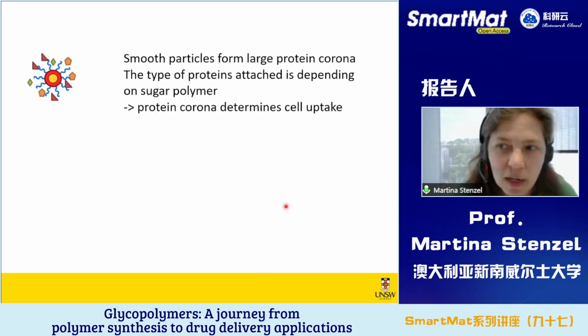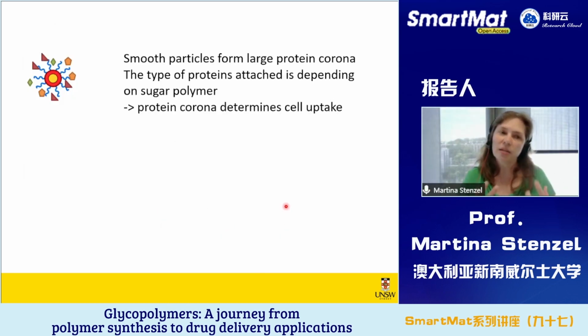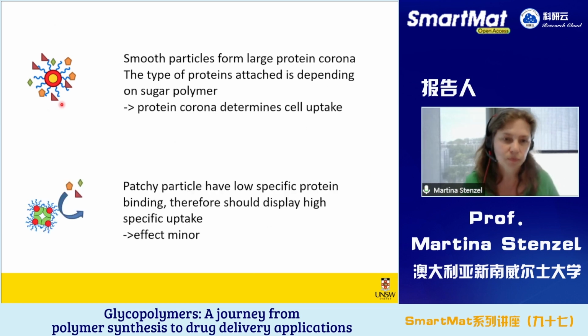So this was a very interesting lesson to learn, that there is a reason why nature's particles have this shape, because smooth particles have a very big non-specific protein corona. And when you have a big protein corona, then suddenly you don't get this specific interaction anymore. At the same time, if you have patchy particles, you have very low non-specific protein binding.